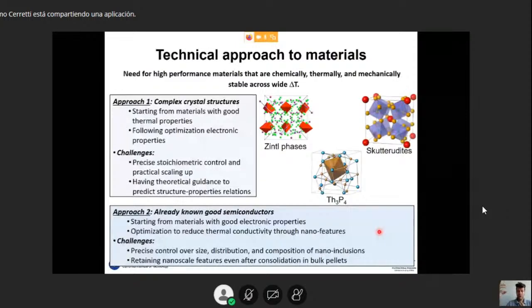The second approach, we start from materials that are already known good semiconductors. So we start from materials that have already really good electronic properties. And the optimization path is focused on the reduction of the thermal conductivity, introducing nano features, so, as I was saying, also compositing or inducing defects in the material. But here also it's hard to have a precise control over the size distribution and composition of the inclusions we want to put inside, especially if we consider that these materials during their lifetime are constantly exposed to temperatures above 1,000 degrees C. And also at this temperature, it might be hard to retain the nanoscale features and avoid that these inclusions grow in size.